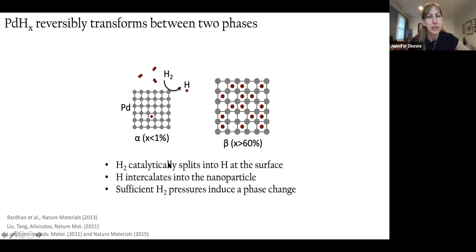So what happens when you're looking at palladium in a hydrogen-rich environment? Well, the hydrogen first catalytically splits into hydrogen atoms or ions at the surface. And then hydrogen intercalates into the nanoparticle sitting at the interstitial FCC sites.